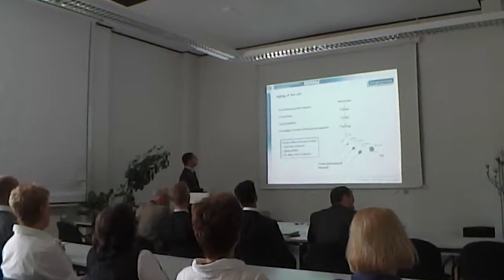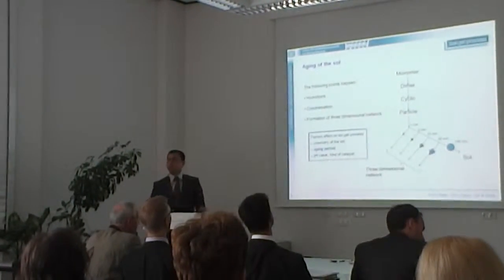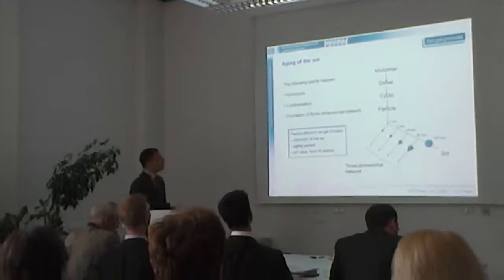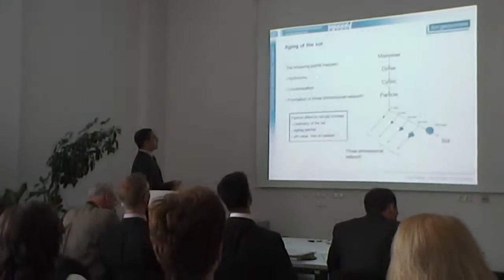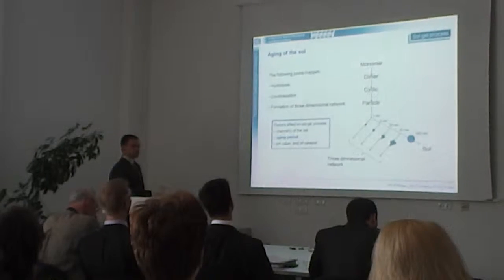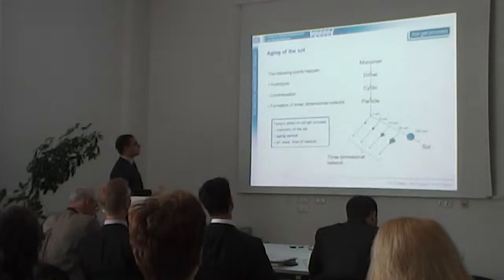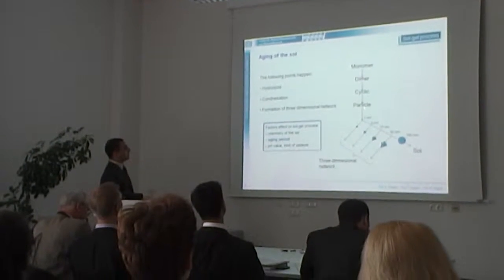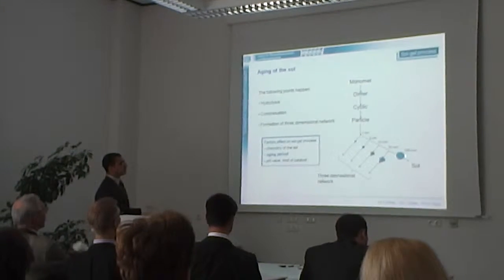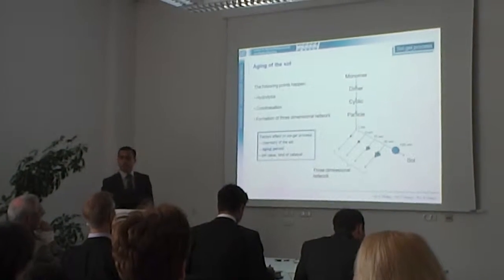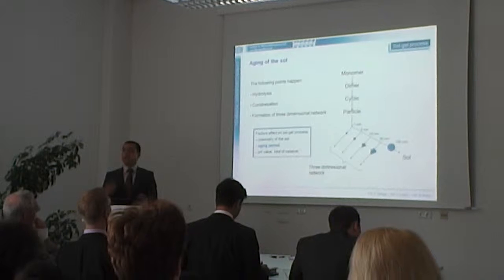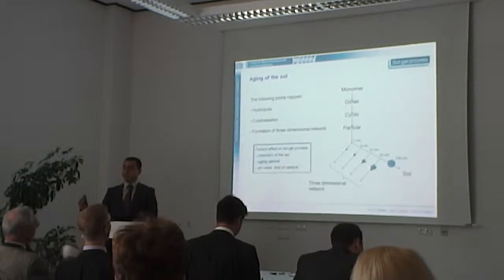The second factor that can affect the sol-gel process is the aging period. Usually the aging period is carried out for 3 or 4 days. During this period, hydrolysis and condensation reactions take place. The monomer turns to dimer and then to particles. The size of the particles can be increased to a few hundred nanometers or a few micrometers. It depends on the aging period, a few days, months, or more.